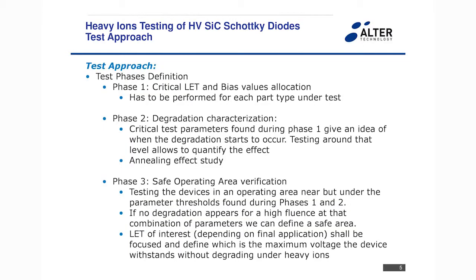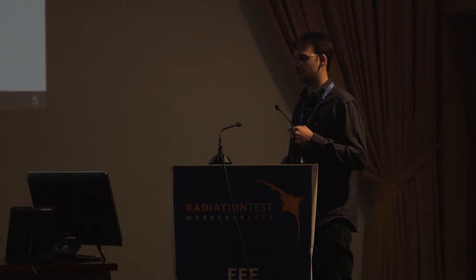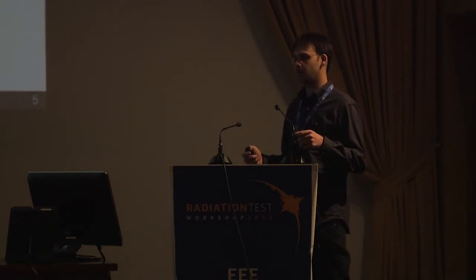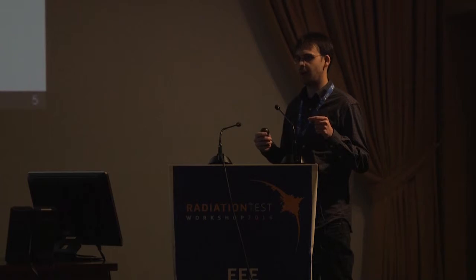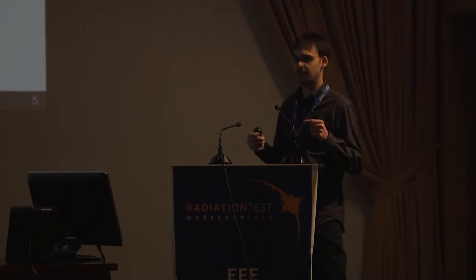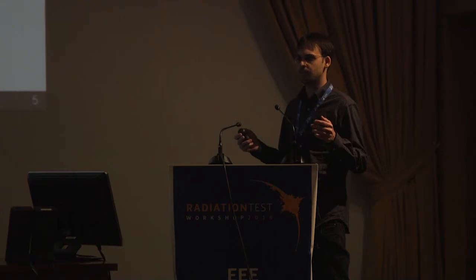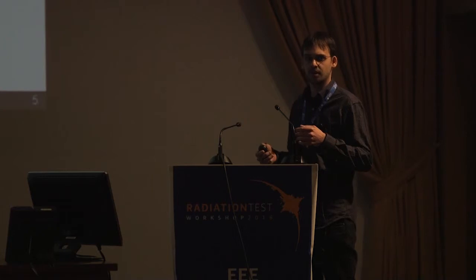Phase two is degradation characterization. Then we go where we expect to have degradation, but not completely, let's say, catastrophic instantaneous degradation or damage, in order to study how that depends on the LET and the bias voltage. And then in phase three, we go where we don't expect to have damage, and we accumulate some fluence in order to demonstrate that the device is not sensitive at that combination of LET and bias.